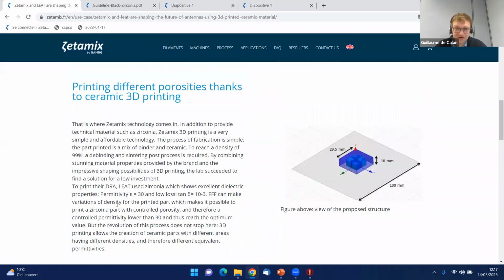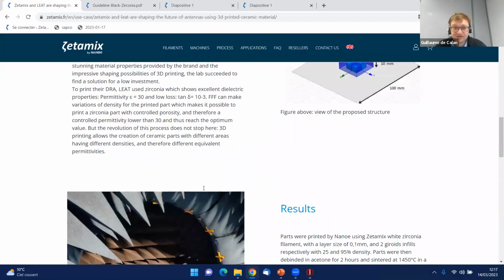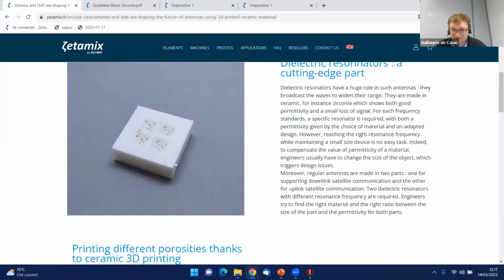The interest for our customer was to actually have a dielectric resonator with two different zones of permittivity. The big square is a bit less than 30, and the small squares needed to be much lower. And so we just tuned the permittivity with the level of porosity we printed. You can see here two zones with different porosities, and there are small holes for the coaxial feed, which you may not see. But that gives you an idea of this. So yes, it's completely possible.